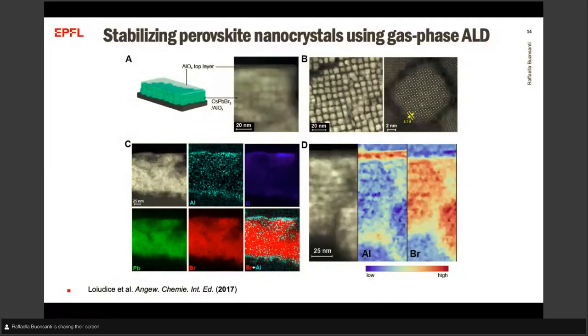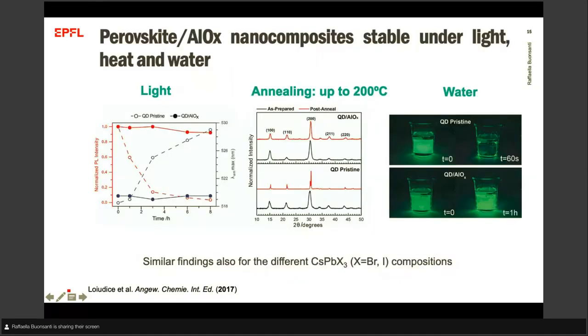We performed a lot of microscopy techniques to make sure that the size and shape of our perovskite nanocrystals were preserved. Some mapping also informed us that the aluminum was present throughout the film thickness and was also capping the film. Thanks to this coating, we were able to make these perovskite nanocrystals stable under light. So basically the PL intensity does not change, and also the PL peak position does not change. They are also stable to sintering because there is aluminum oxide in between the quantum dots, so they don't sinter when we anneal them, and they remain relatively stable in water.